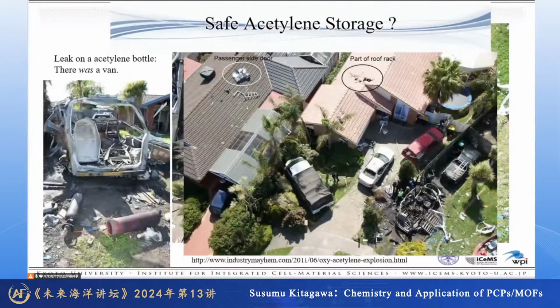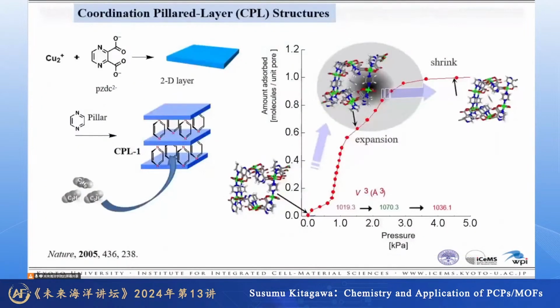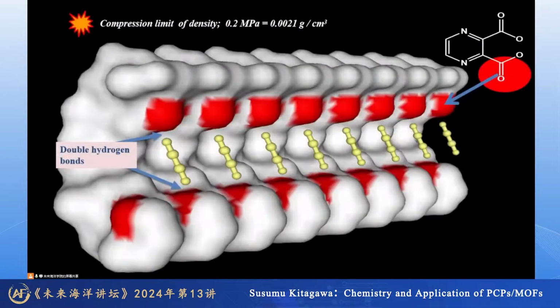The first one is to explore acetylene. Acetylene is dangerous, as you know. At room temperature, at 2 bar, abrupt explosion occurs. Even in a safe cylinder, this kind of explosion occurs. It's a very dangerous case. So we synthesize this type of framework and introduce acetylene. This is the pressure versus absorbed amount of acetylene. Acetylene is absorbed in this way. This is a crystal structure, with acetylene on the surface of the channel here. The acetylene hydrogen forms hydrogen bonding with free oxygen, so a double hydrogen bonding system here. The concentration is 0.4 gram per cubic centimeter, but the compression limit is 0.0021 gram. So it is 200 times larger than the dangerous case, but still stable.